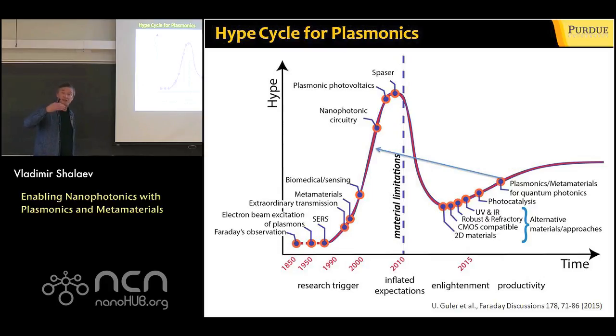when you place Raman active molecules, and Raman scattering is just when you irradiate molecules with light, it's shifted because molecules have these vibrational degrees of freedom, and it's a wonderful fingerprint of any molecule. But when you place these Raman active molecules on rough metallic structures, nanoscale structures such as a rough electrode, then the intensity of Raman scattering increased by orders of magnitude.